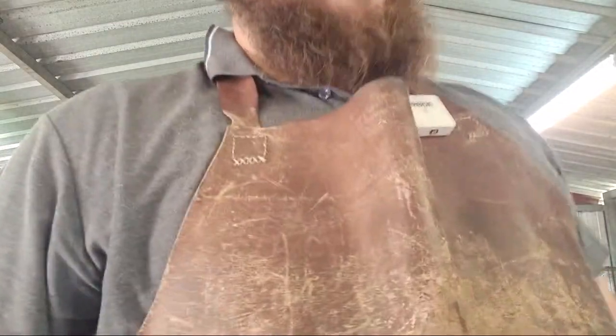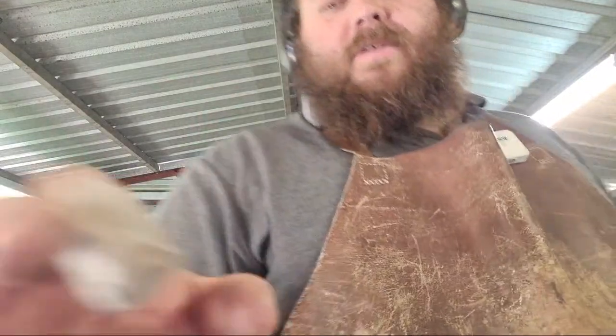That's all it does, Matt, is it changes the pattern. If you're making crushed W's, if you just squish straight down on the ends of the layers, you may get some cupping, but there's not a guarantee. Whereas if you squish the corners in, what you do is create a C shape, right? Like if you imagine the corners of the square getting squished in, then when you squash that down, those C's become more and more pronounced. And so then when you stack them together, you have these C's, which then become W's. If you squish straight down, there's a good chance you could literally just upset them straight down, and then all you do is be stacking lines on top of each other, and it just would not look good. So yeah, taking those octagonal corners is important.